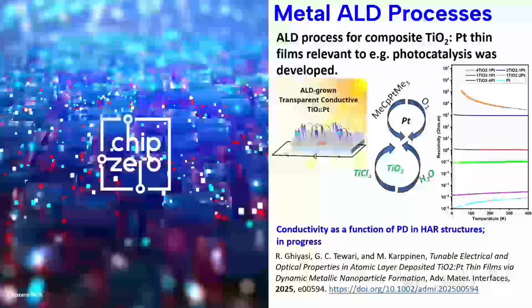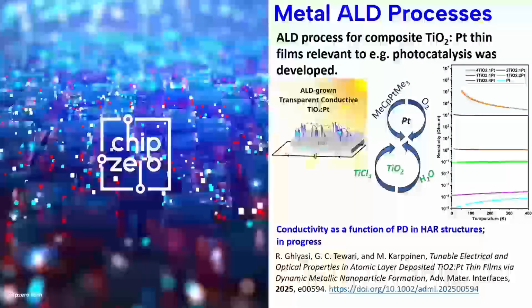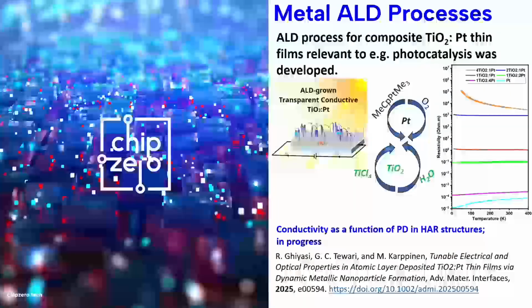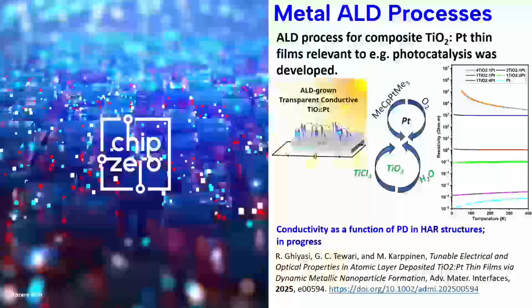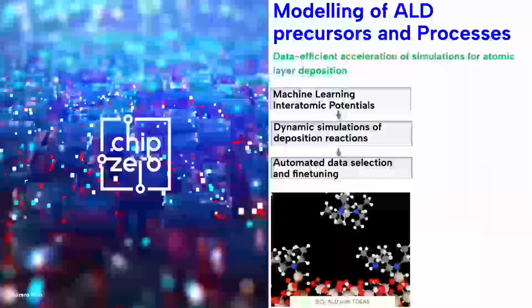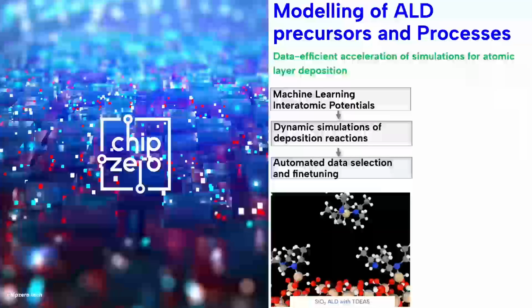Another goal of the project was metallic ALD. As part of this project, we were able to develop a new process for platinum-based metallic films, using titanium dioxide in superlattice structures. So here we can go from insulators to conductors by changing the ratio of platinum and titanium dioxide. Now we are also aiming to study the conductivity of these platinum-based thin films in high aspect ratio structures using the pillar hall chips. That project is ongoing. So now I will hand over the mic to my colleague.